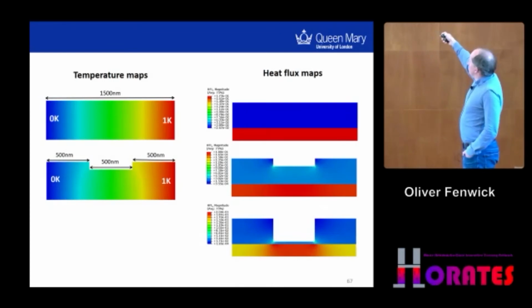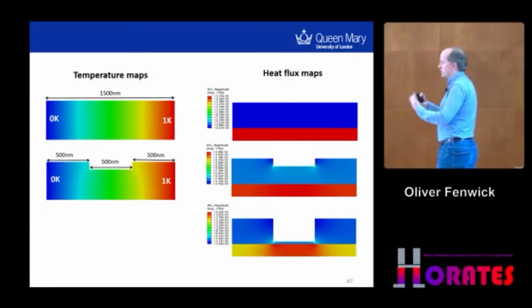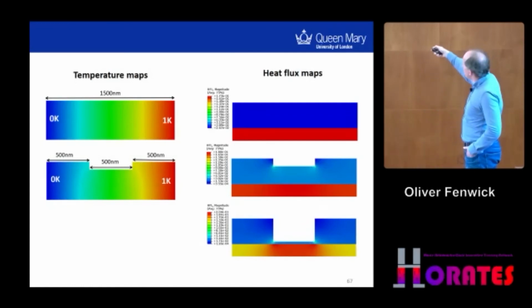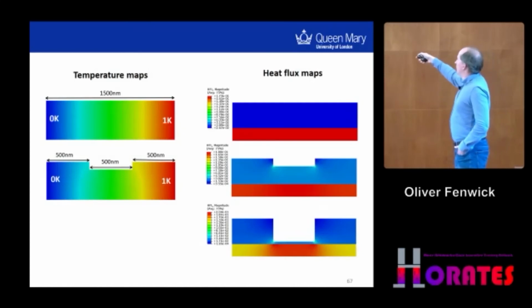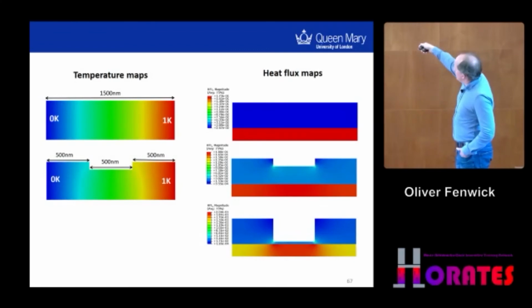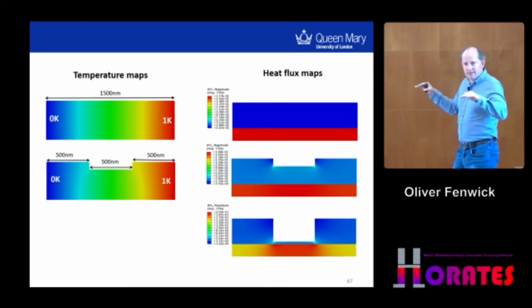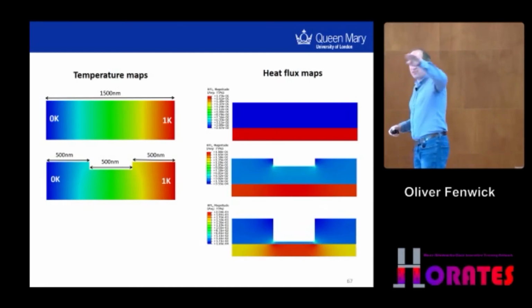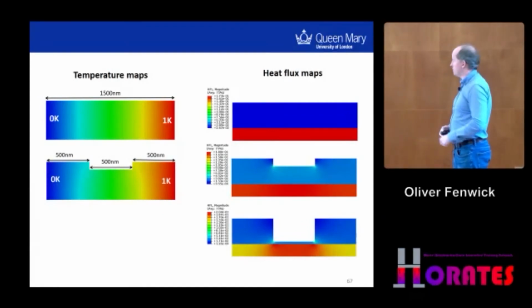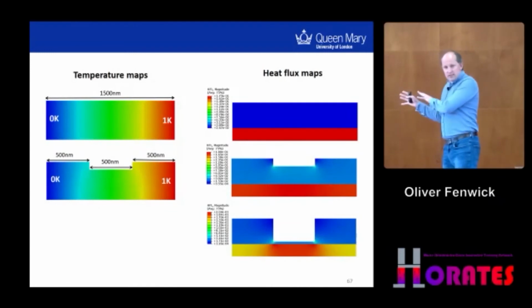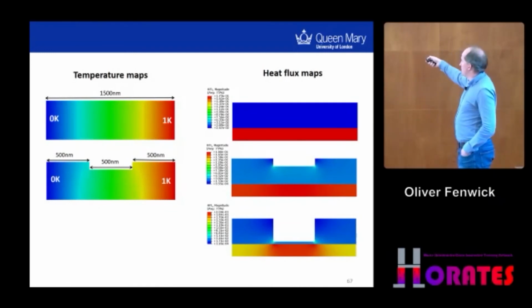Now, if we look at the heat flux, the blue area is low heat flux. We have low heat flux in our polymer film, of course, because it's low thermal conductivity. We have high heat flux in our membrane, which has thermal conductivity of 2.6 watts per meter Kelvin. Put a defect in there, and you start to see little changes. You get high heat flux around the corners of the defects and low heat flux up in the corners at the top. And when you make a very extreme indentation, you can even affect the heat flux through the membrane. So the membrane here is accommodating heat flux from the polymer film that can't get through that constriction. It's obviously a slightly different situation to a fully suspended film, where that constriction might have an even more severe effect on the thermal property measurements.